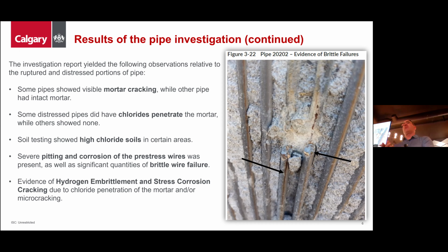Unfortunately, and this is part of forensic analysis, we found some parts of the pipe that had hydrogen embrittlement or stress corrosion cracking, but there was no evidence of structural deficiency within the pipe. Then we found some parts of the pipe that had structural deficiency, but no signs of SCC or hydrogen embrittlement. And then we had portions of the pipe that had both. So the answer is it's inconclusive to say that SCC was actually part of the pipe break itself. We were hoping to be able to pin that and say, yes, that's definitely the cause.